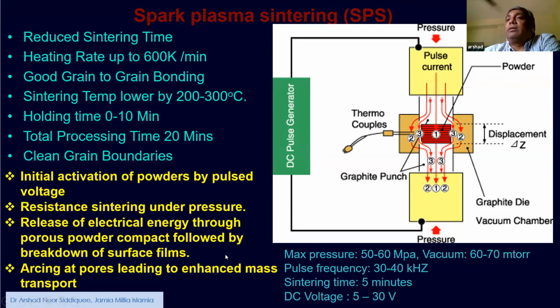This is the typical specification of the spark plasma sintering parameters, and this is the characteristic. These are the advantages. The sintering time is reduced, the heating cycle is very fast, and grain to grain bonding is very good. Sintering temperature is very low. Temperature should be low and time should be short, which stops the grain growth, and the holding time is also very short. The total processing time is 20 minutes. Clean grain boundaries. So these are all the advantages.